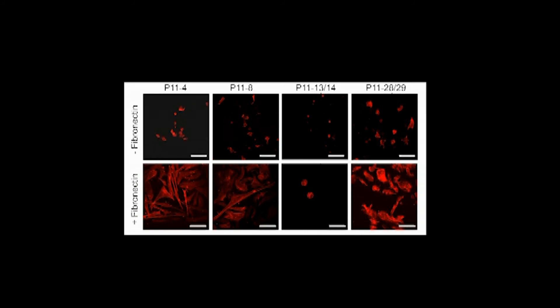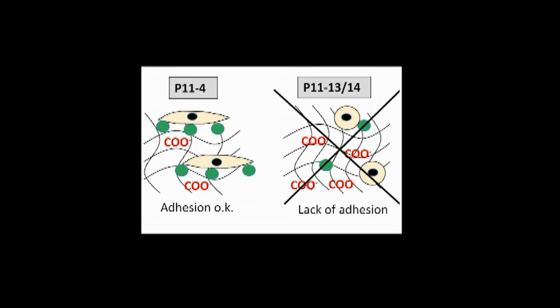Cells cultured under self-assembling peptide hydrogels without pre-incubation of fibronectin were really rounded shape, whereas with pre-incubation of fibronectin cells showed a stretched actin filament. Further experiments revealed that the surface chemistry regulated protein adsorption capacity and thus also in turn the cell morphology.